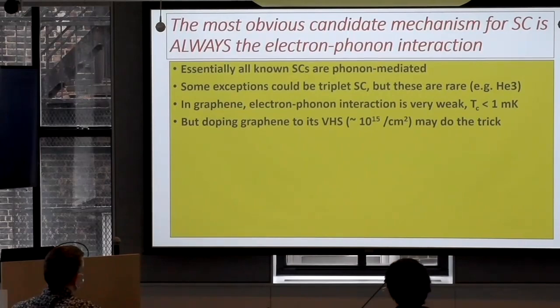150 Kelvin? Okay, I stand corrected then. So I have to ask Matthias, why is he giving me wrong information? Well, again, I suspect that part of the issue, this goes back to work that Xue and others have done, is that the superconducting state, which is found, is preempted by another phase, which doesn't show up very well.